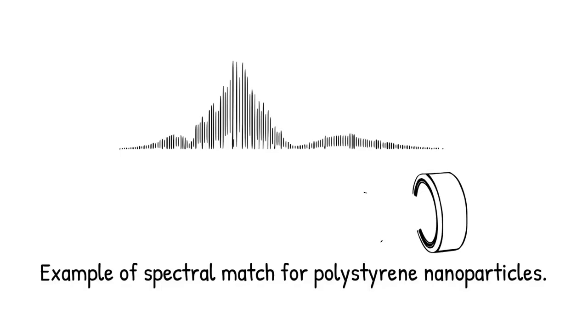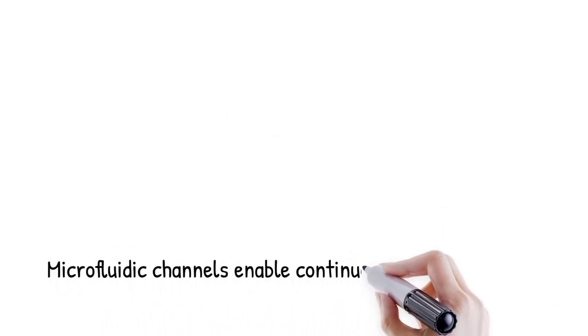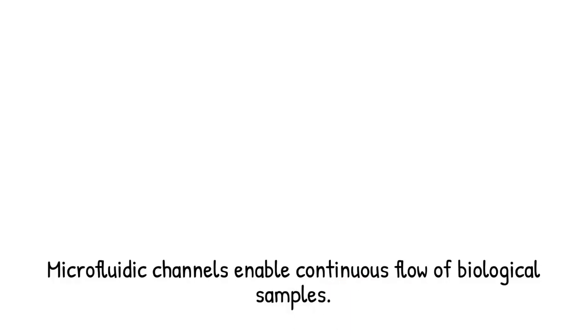This chemical fingerprinting confirms the identity of each trapped nanoparticle in real time. Trapped nanoparticles from urine samples produced a distinct peak at 1605 cm⁻¹, matching the polystyrene reference spectrum.